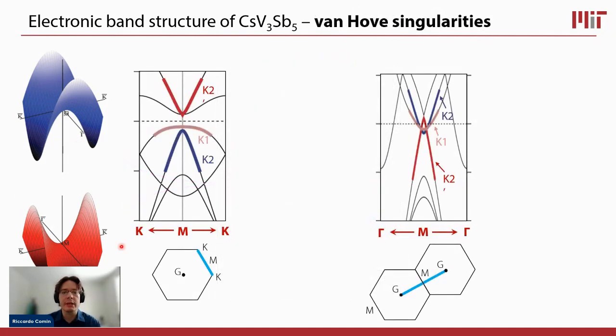If we look closely in the DFT at these dispersions along two main directions, the K point to M point to K point direction, which would be this direction in this plot and this direction in this plot, you see that one type of Van Hove singularity forms a top, and the other has a bottom. The opposite happens along the perpendicular direction. So the bands that have a top over here now have a bottom in the dispersion over here, and conversely, the red band that had the bottom over here in the perpendicular direction has a band top.